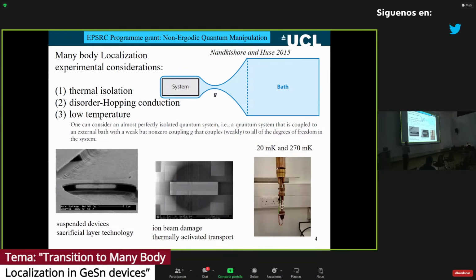What we're also doing is introducing disorder by ion beam damage. And if you saw my talk on Monday, you would see some of the structures that we're able to make at high dose levels. At low dose levels, we can introduce disorder, and it's quite good because we don't lose carrier density, we just increase disorder, so we lose mobility. The charges lose their mobility to move, but we don't lose charges. So those are the basic ingredients that we need to consider.